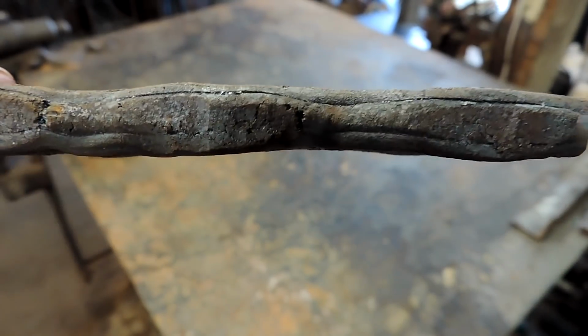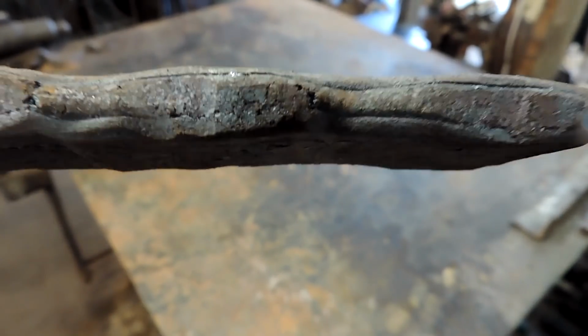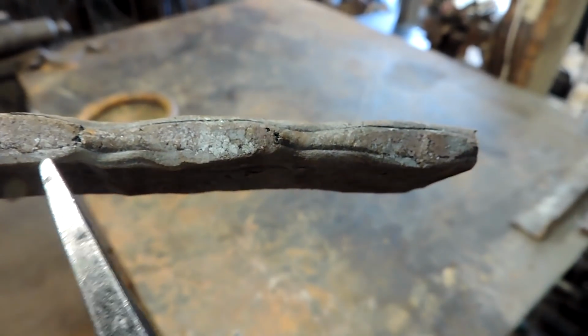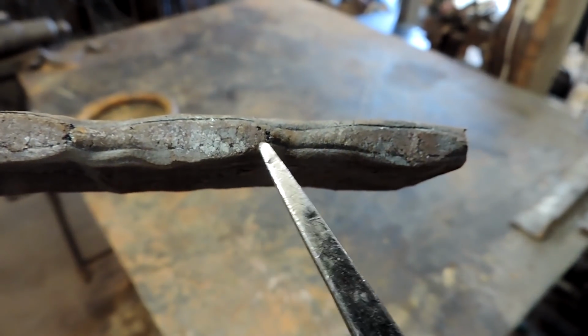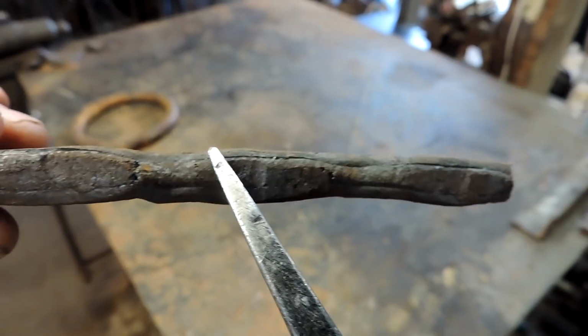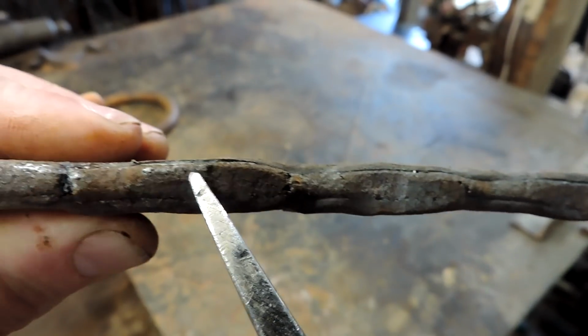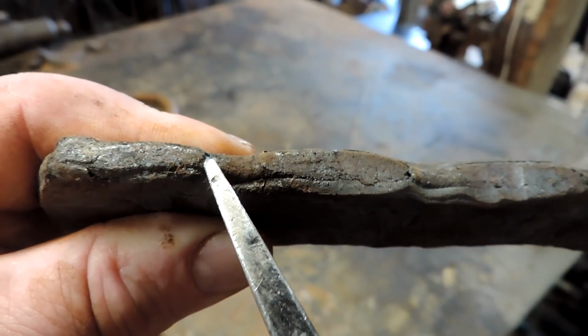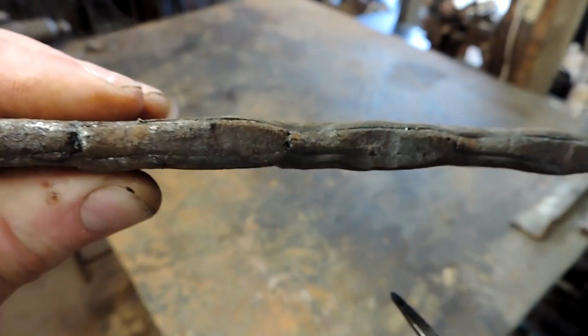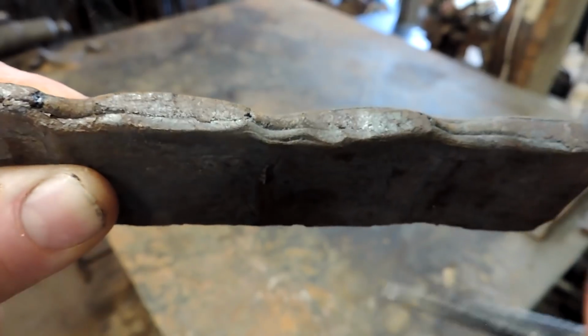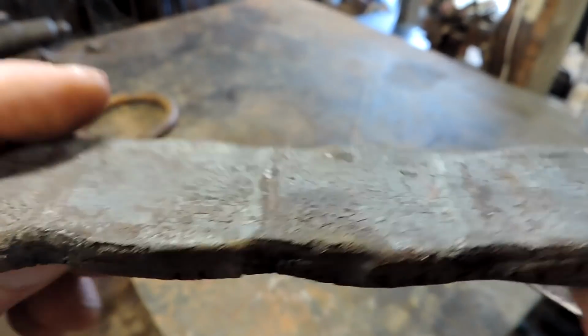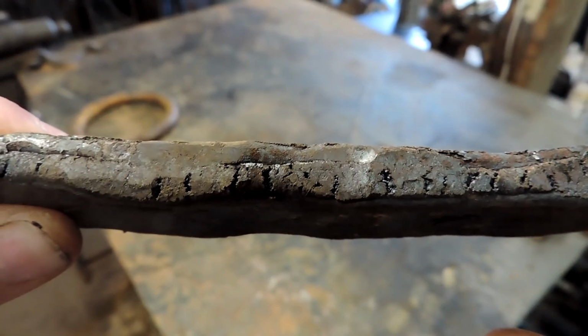Okay, so after we pressed it out, I cut about a 6-inch piece off the end of this. We're not going to need that much for the knife. And you can see the laminations here. And this is right off the press. And there is some cracking on this side. So we flip it over, and it cracked quite a bit on this side.